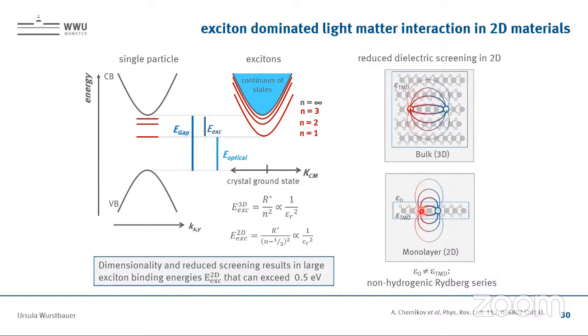And remind, a composite boson is an exciton. It's important if you think about changing the quasiparticle statistics. Something else I should mention, just because of the dimensionality here, the Rydberg series is a little bit altered. So with that, we already get an enhancement of the binding energy by a factor of 4 just by the dimensionality, just to give you an idea.